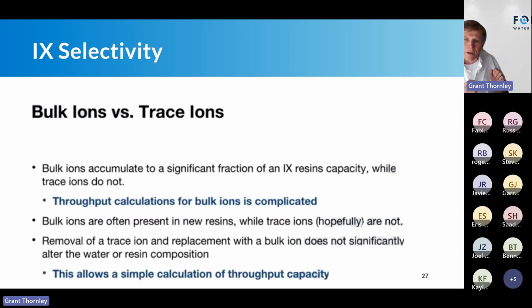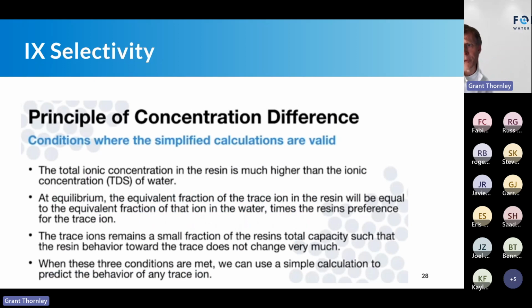So removal of trace ions does not significantly alter the water or the resin composition. This allows a simple calculation on capacity. So the principle of concentration difference: the total ionic concentration in the resin is much higher than the ionic concentration, the TDS, of the water. So there's more exchange sites in the resin, or ionic strength in the resin, than the concentration. So at equilibrium, where the resin's been loaded up, the equivalent fraction of the trace ion in the resin will be equal to the equivalent fraction of the ion in the water, if the thermodynamics have equalized. So the resin preference for the trace ions remains a small fraction of the resin's total capacity.